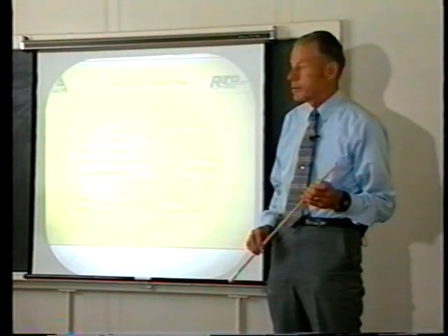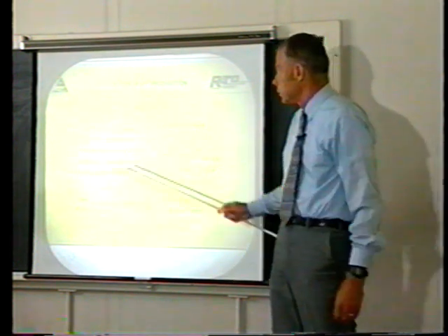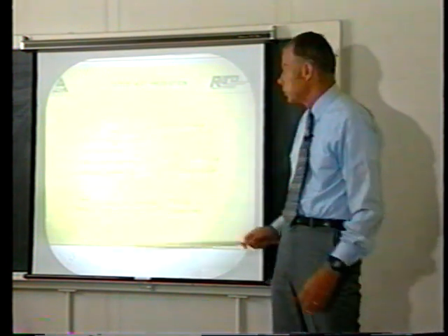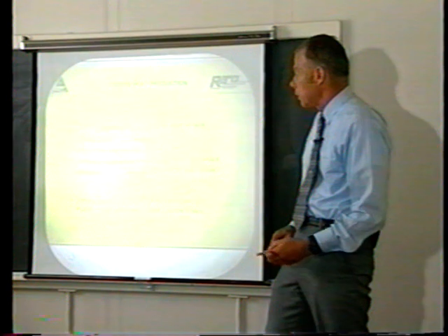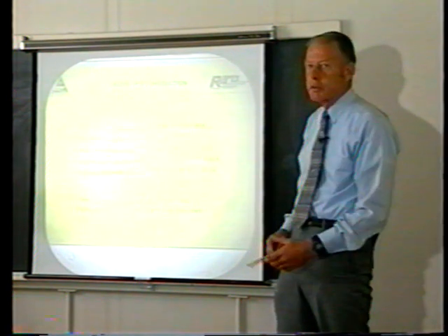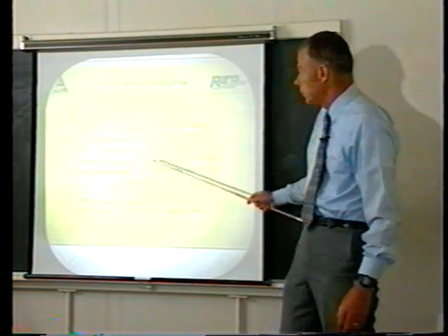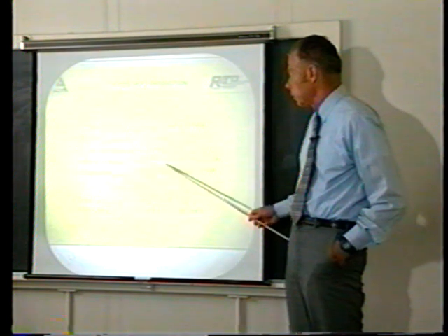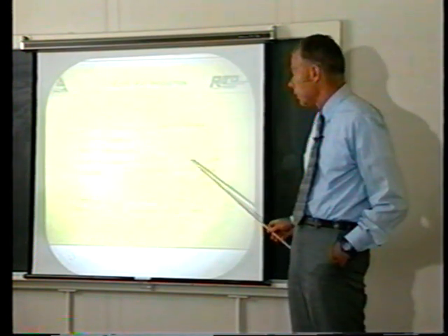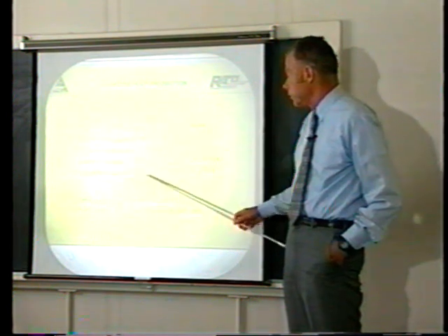Our excess heat production typically was 5 to 10% larger than the input power. Our largest excess heat effect was a 30% excess heat. This generally gave 1 to 5 watts per cubic centimeter of palladium that was used. Generally, we needed an induction period of 6 to 14 days before we ever saw any evidence of excess heat. We had a threshold current density. We did not see excess heat unless we were operating at a current density of 100 milliamps per square centimeter or larger. And our success varied with the source of the palladium that we used.